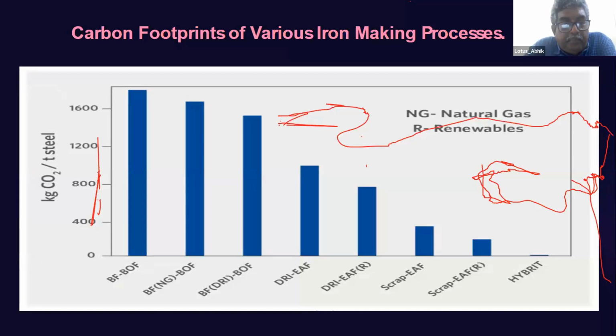Now, here is a diagram which is showing the carbon dioxide per ton of steel produced by different processes of steel making. Okay. So there are different routes. First is the BF, BOF, which we described, which is standard and general. If you go to any integrated steel plant, you'll find that BF, BOF route. This is, as I said, almost 2 tons of carbon dioxide they produce. Then the route where, instead of coke, they are using natural gas. Then this DRI route, DRI-EAF, they are also emitting carbon dioxide, but not up to the level that we are getting from the BF route.